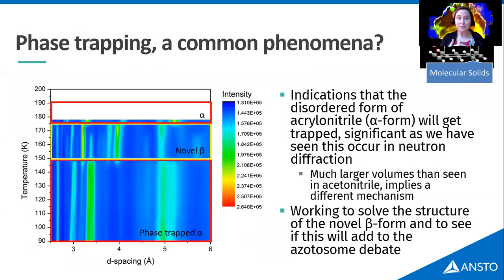So we've done a neutron diffraction on the hydrogenous sample here again. And what we've discovered is we do see phase transitions, we see a new form, and we're having some trouble solving it. But the clue that we got from the acetonitrile has really helped here, because now what we think is happening in interpreting the acrylonitrile data is we think that alpha form, that disordered form, so we're now calling them alpha and beta, that high temperature form is actually being trapped at lower temperatures.